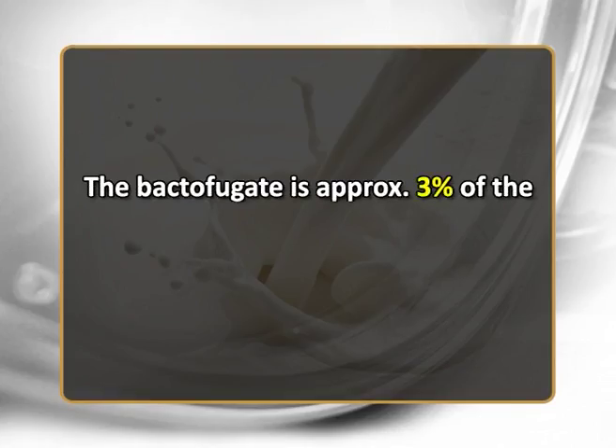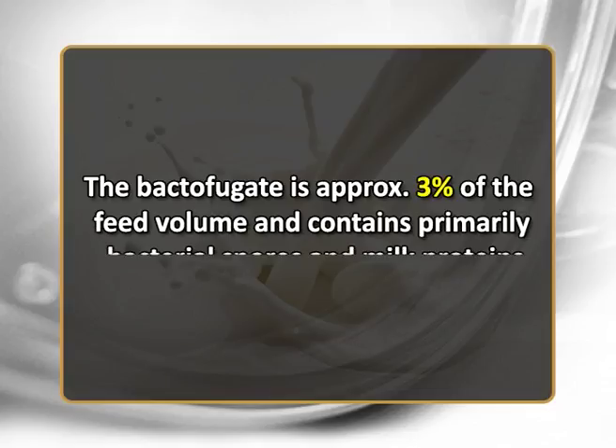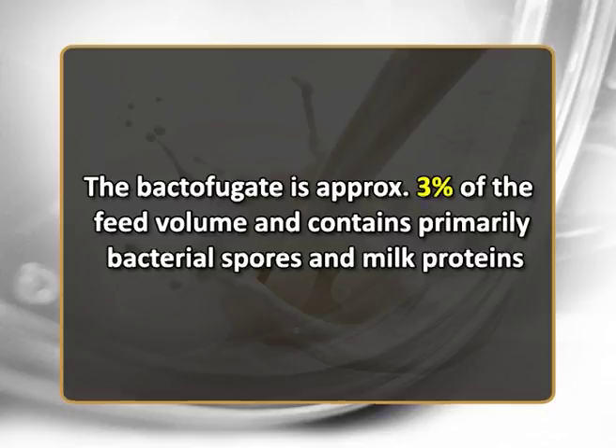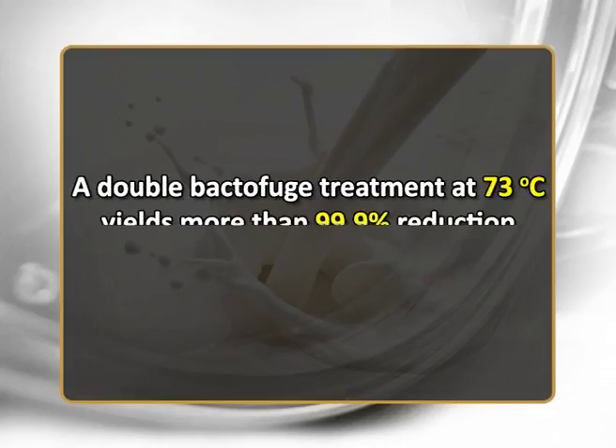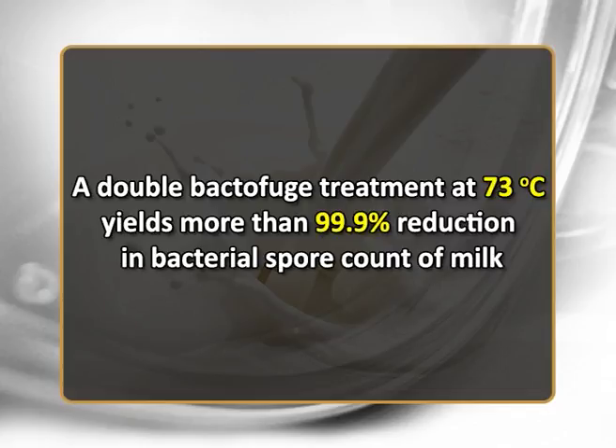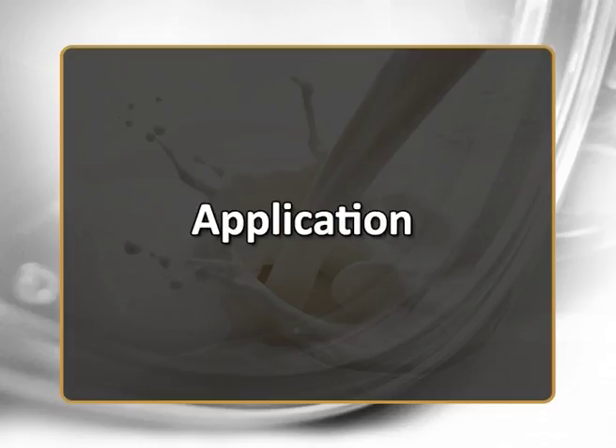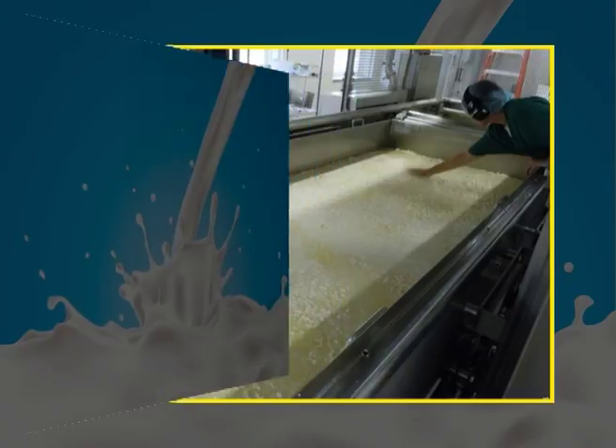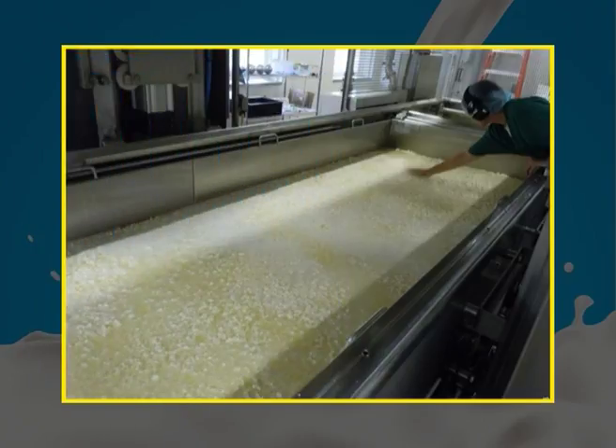The bactofugate is approximately 3% of the feed volume and contains primarily bacterial spores and milk proteins. Anaerobic spores are removed to an extent of 98 to 99%. A double bactofuge treatment at 73 degrees Celsius yields more than 99.9% reduction in bacterial spore count of milk. Application. Cheese making, where removal of anaerobic spores from milk is useful in avoiding the problem known as late blowing in hard and semi-hard cheeses.